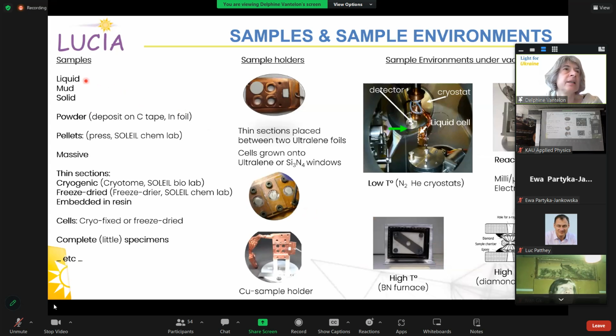So the samples, as I said, can be numerous: liquid, mud, solid. We can use powder and deposit it on carbon tape or press it into a pellet. We can work on massive samples or thin sections that can be cryogenic, freeze-dried, or embedded into resin. We can work on cells, and I will show you some complete little specimens, which can enter into the little space of the vessel. I have to mention that the constraint is that we are working under vacuum because we are working in the tender X-ray domain. The samples are installed on copper plates with variable designs adapted to the different samples we can measure. And we have also developed some sample environments compatible with vacuum to work on samples under constraints, such as temperature or pressure.